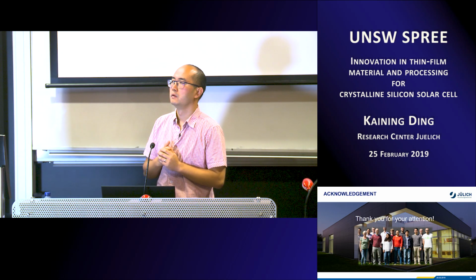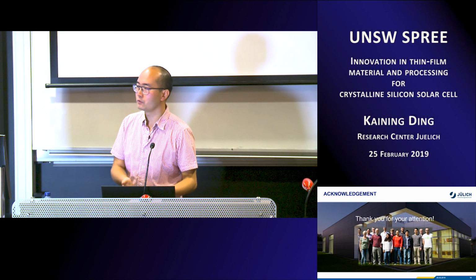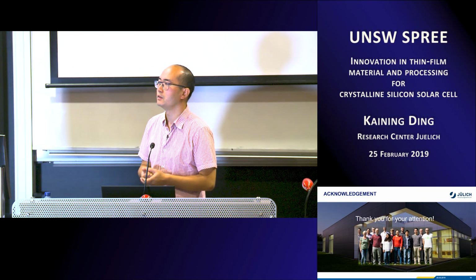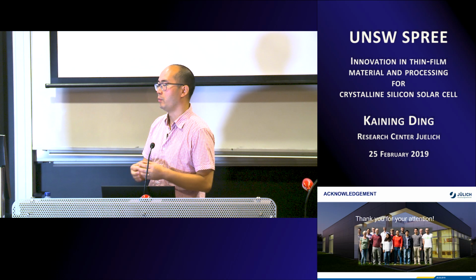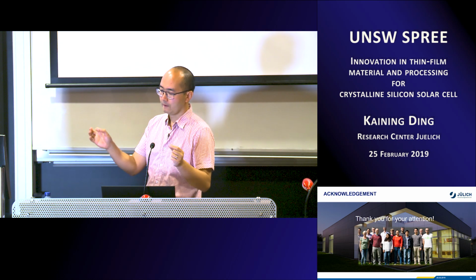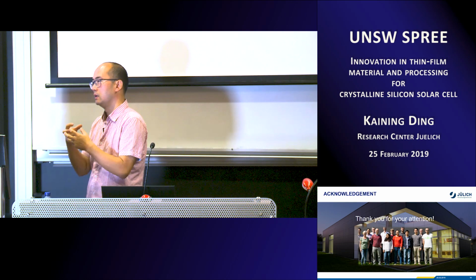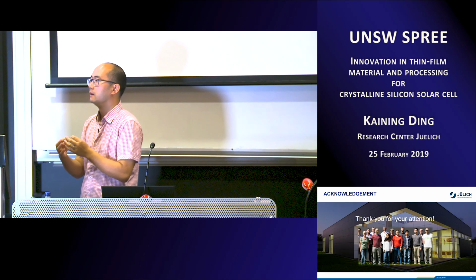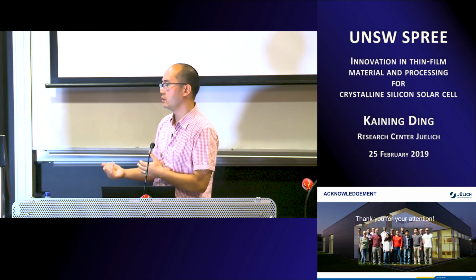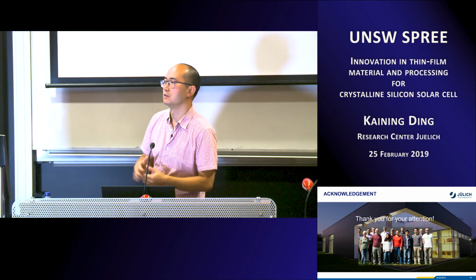Is it basically evaporation, what you're doing with that? So it's just a wire. It's a debate. I think there are two names for hot wire CVD. Some people call it hot wire CVD, and other people, especially in Japan, call it catalytic CVD. I think it's a matter of operation range. If you are operating at temperatures like 1,400 degrees C, a little bit below or above, you are talking about catalytic effects. It's not only a thermal dissociation of your precursor at the surface, but also some chemical effects. But if you go to very high temperatures, like 1,800 or 2,000, maybe it's purely the temperature doing the job. So it depends.